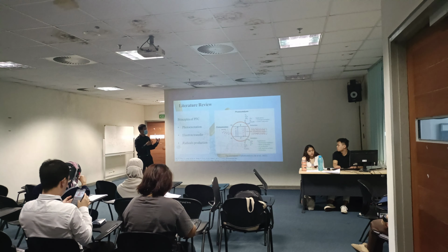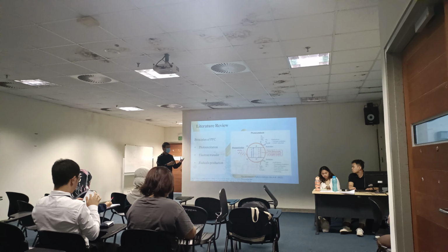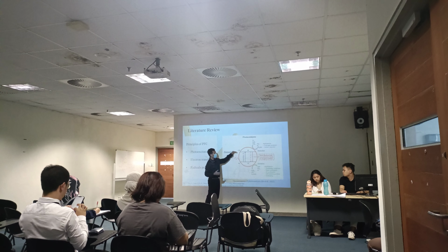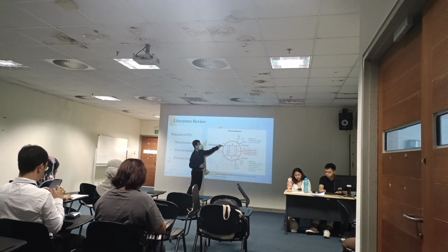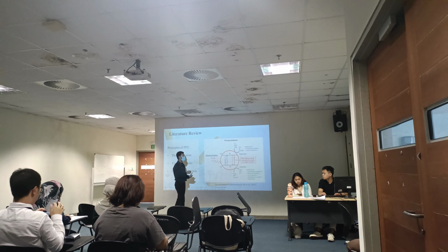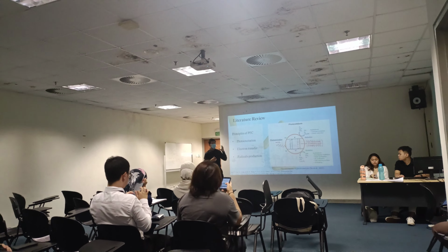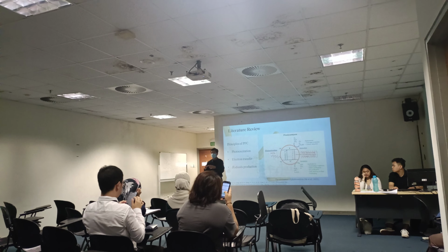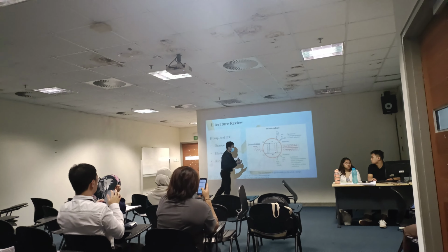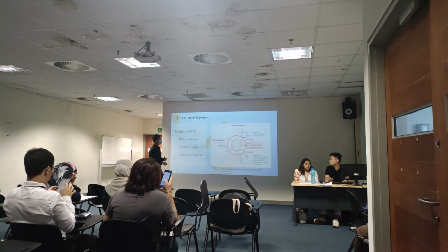It works by the photoexcitation process, whereby it occurs during the irradiation of the light onto the surface of the photoanode, thus producing the photogenerated electrons from the valence band to the conduction band, and then the photogenerated electrons from the conduction band will travel through the external circuit to generate electricity by reaching the cathode side. Then, for the radicals production, the photogenerated electrons that have reached the cathode chamber will react with the oxygen molecule to produce the superoxide radicals, while the photogenerated holes at the valence band will react with the water to produce hydroxyl radicals to degrade the wastewater.